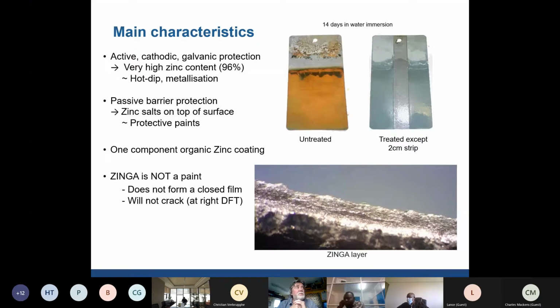Okay, so the protection is galvanic. The Zinga does generate a voltage, and the voltage is flowing through the steel 24 hours a day. And because that voltage is flowing, it's physically impossible for you to have corrosion cells setting up anywhere on the steel. It's physically impossible, so you cannot have corrosion. And that's in the atmosphere, it's underwater, and we even have some jobs in the sea. And the zinc just depletes every month, slowly from the top, always from the top. So the metal is never compromised in any way.